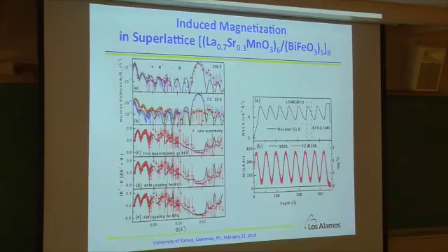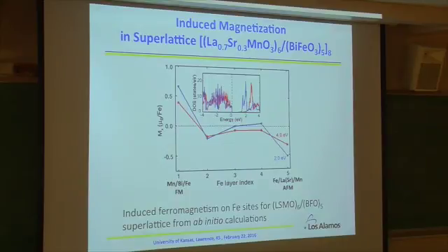And then we do the theory. We say, well, what's really going on there? Here is some calculation, using ab initio calculation. The interesting thing is that it depends on how you terminate the interface. For example, if the LSMO is the top, the middle layer, and the interface is terminated by bismuth oxide, we believe, based on the theory at least, it is ferromagnetically coupled. However, if you go to either lanthanum or strontium terminated, then it is anti-ferromagnetic coupling.